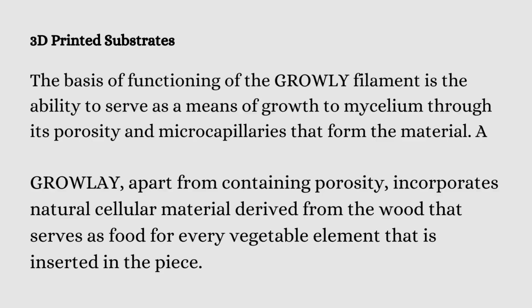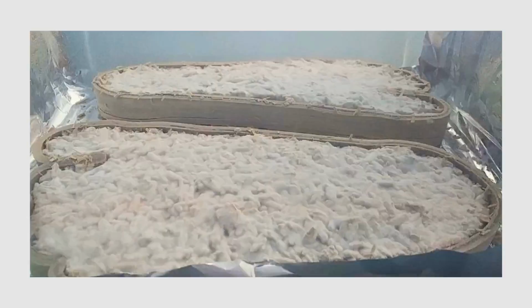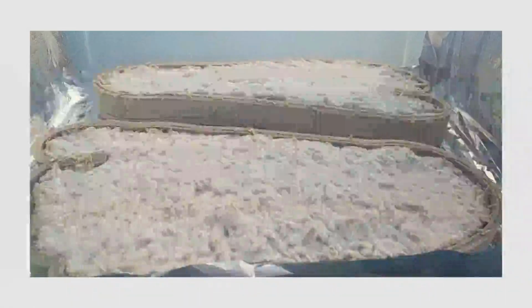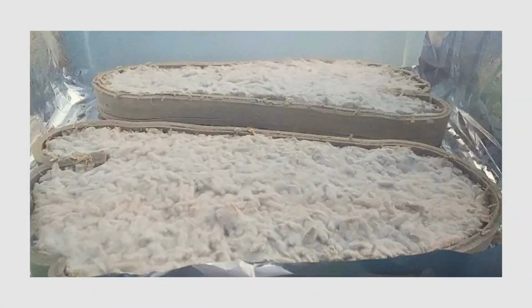So once you've printed that out, you need to soak this for at least 12 hours. And this is going to allow the material to look like this. Now you can see this is a bit bloated. It looks a lot more soft, and it is. It's very soft once this happens, which is so interesting. This is a very interesting material to print with, because here it's very, very hard and brittle, and then once you soak it, it's very spongy, and it even changes color.